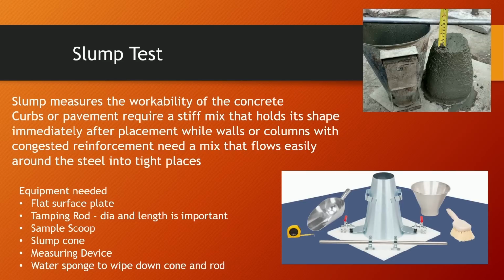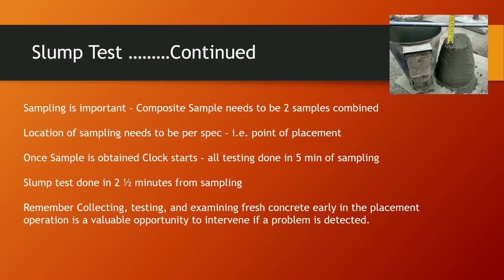In order for a slump test to be done, you have to have a flat surface plate, a tamping rod. Diameter and length of the rod is important to ACI. You need to have the sample scoop, the slump cone. You need to have a measuring device, tape. You need to have a water sponge to wipe down the cone and the rod. So if your third party's rolling up and they don't have these things, they're already messed up. It's already bad news.